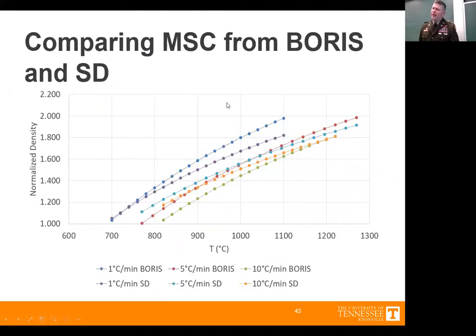When I looked at comparing data, so this is master sintering curve data from the Boris system versus the sintering dilatometer, again, I found that the data was very, very comparable. They weren't exactly the same. Obviously, the equations were slightly different, but all of the data was very close within the margin of error, depending on the different heat rates from system to system. Hard to figure out right off the bat what some of those reasons might have been for the difference between the sintering dilatometer and the Boris system, but I'll talk about that towards the end.